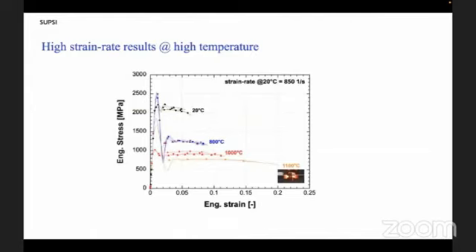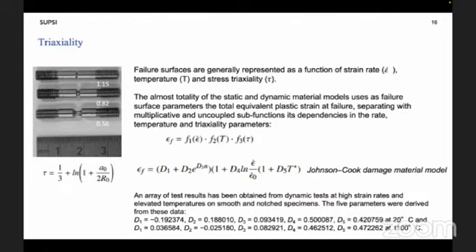The stress triaxiality at the center of the net section can be calculated by the formula proposed by Bridgman. And the material parameters of the Johnson-Cook damage model were obtained by using the experimental data. And according to these parameters, we have created the failure surface shown in this slide, on the left for 20 degrees Celsius and on the right for 1100.